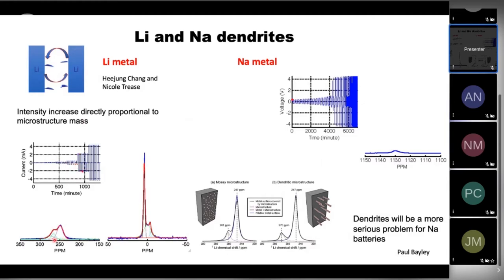Now watch what happens when the current density increases. We see a new signal, and that's the signal due to the dendrite growing. So effectively, we're increasing the surface area of lithium metal because of these high surface area dendritic structures, and the signal grows. Interestingly, at the same time the signal grows, you can also see an increase in the signal around 0 ppm. And this is the growth of the surface electrode interface passivating the lithium.